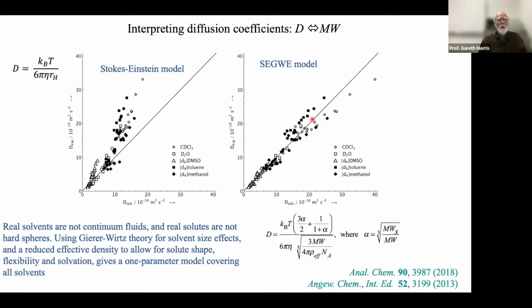So this Gierer-Wirtz theory, that SEGWE method, is finding quite a lot of use. Again, one has to be aware of its limitations, but it does give us fairly good diffusion molecular weight relationships for a very wide range of small molecules, less than about 1,000 molecular weight, and solvents. Of course, we can do much better than this if we pin our problem down. If we say we're only going to look at N-alkanes in deuterochloroform, then we can get a very accurate relationship, but we don't often spend time measuring such systems.